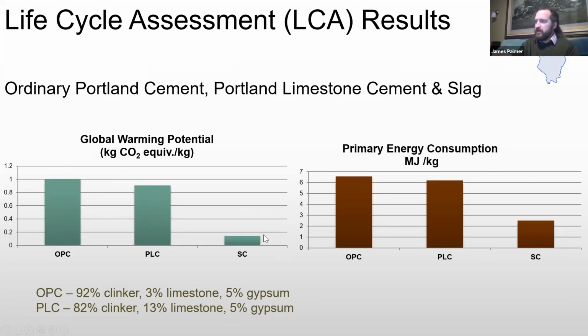The other interesting thing here is this SC represents slag cement. So slag cement, it is an SCM that improves various factors of the concrete and has in the past actually reduced the CO2 content, even though that's not why it's being included in the mix. But if you really want to push the envelope and further reduce your CO2, those SCMs, secondary cementing materials, can further reduce the impact of your concrete on the environment.